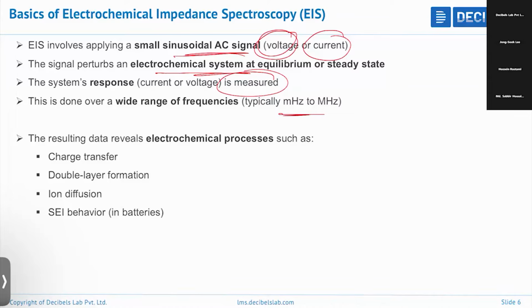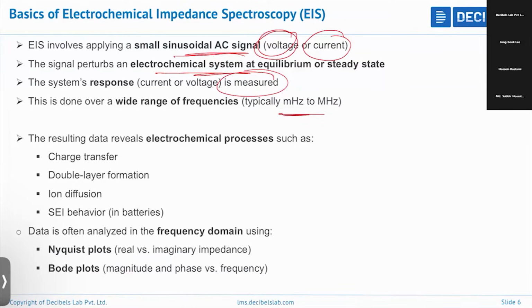The resulting data from this electrochemical process reveals that we can understand the charge transfer, that is RCT resistance, double layer CDL, and Warburg ion diffusion and SEI behavior in batteries. This information is often analyzed and extracted from the frequency domain plots. That is the Nyquist plot, which plots real versus imaginary impedance. And then we have the Bode plot, which is the magnitude of impedance and the phase versus frequency. We can extract two pieces of information from this Bode plot.